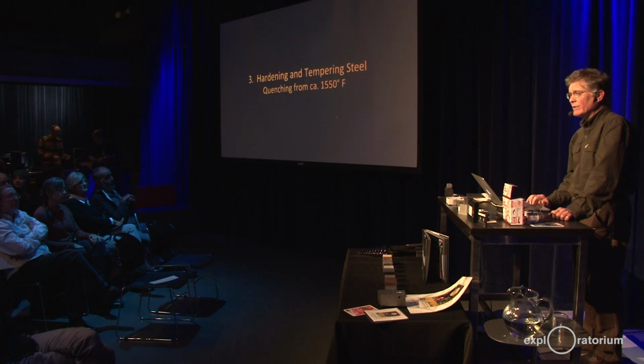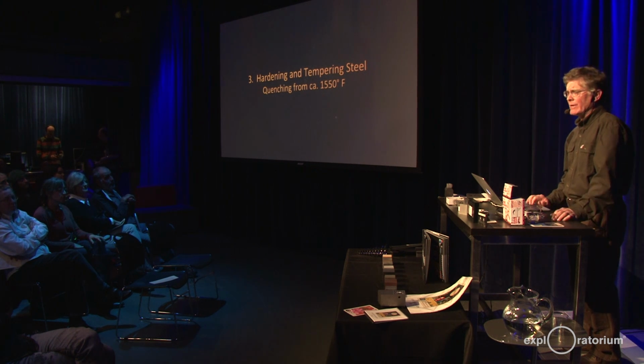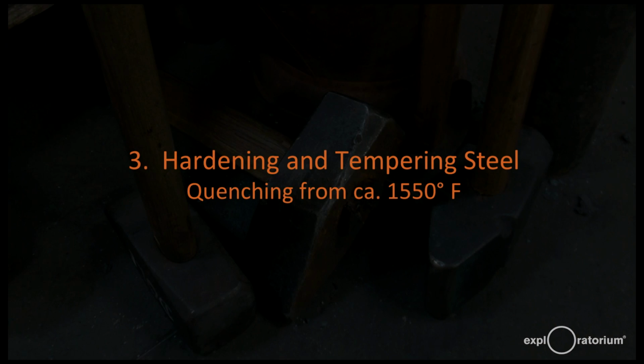So steel might have been 0.45% carbon to 1.2%, and it was capable of being hardened for use as the cutting edge of like an axe or knife, or an impact tool, the face of an impact tool such as a hammer. To harden the tool, the steel part was heated to a specific incandescent red heat called the critical temperature, again about 1550 degrees. And it just turned out that that's where the steel lost its magnetism. So for at least 100 years, people have known to check for that temperature by testing it with a magnet.